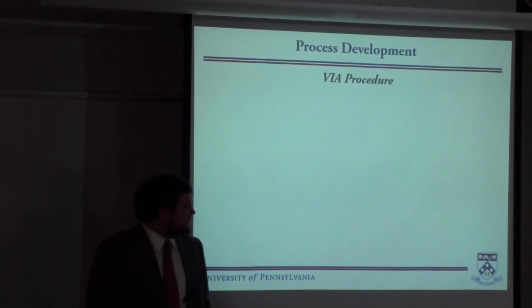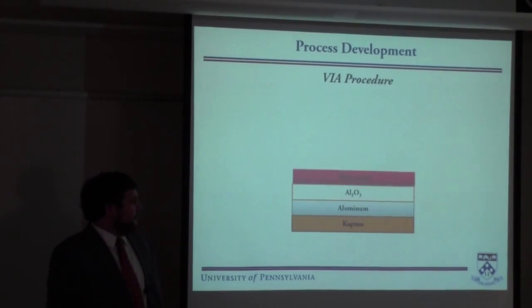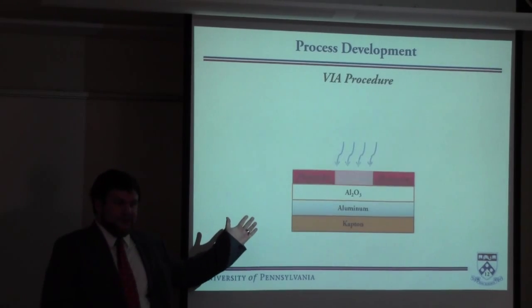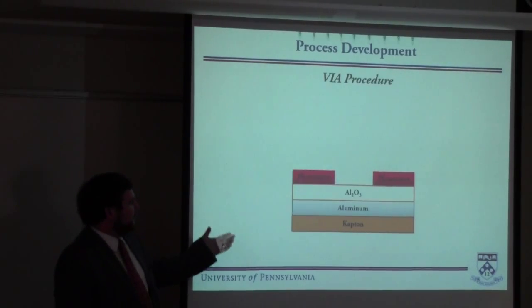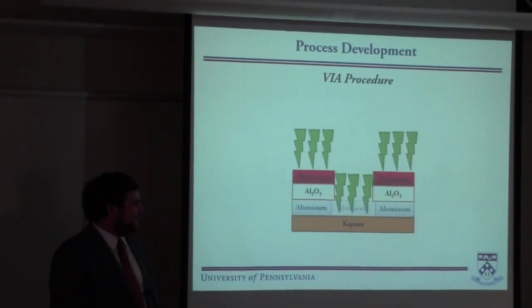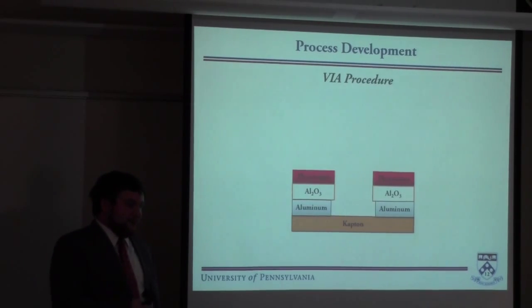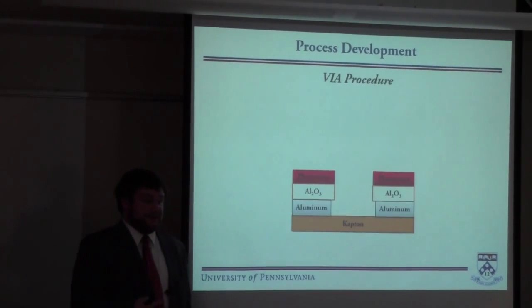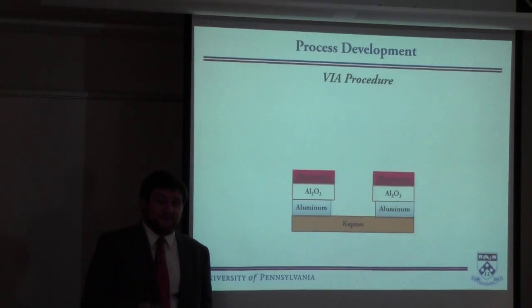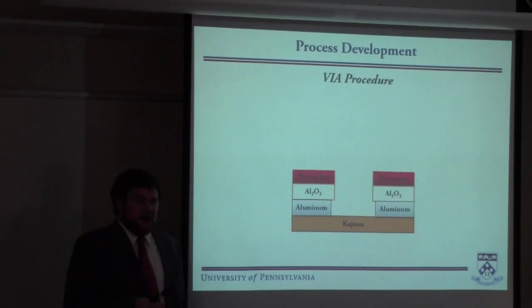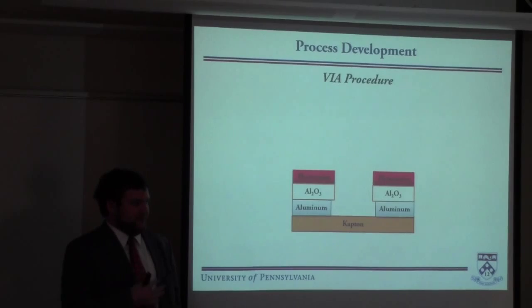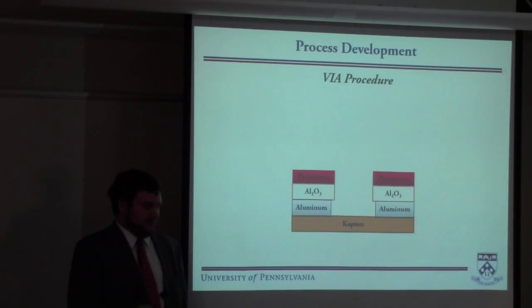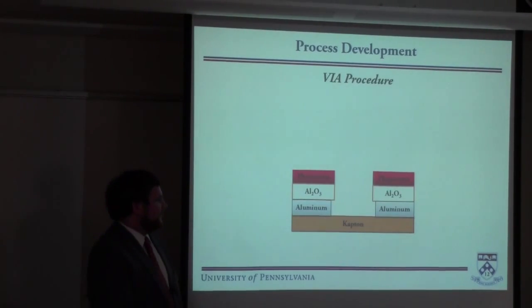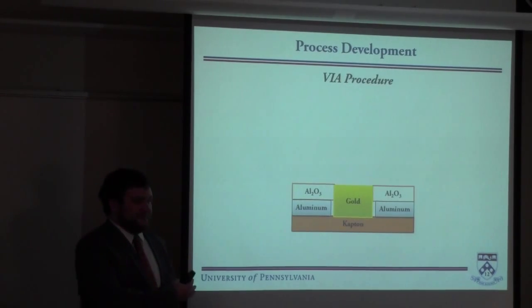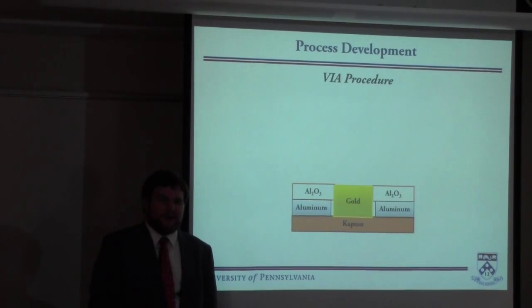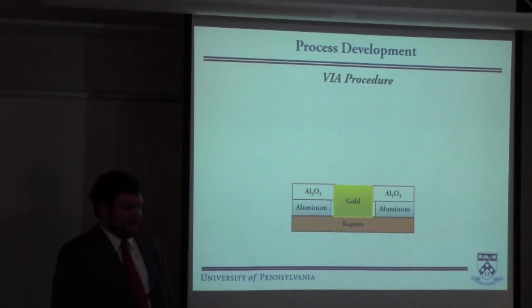So that led to some issues, because when we want to make a hole in the Al2O3, and we pattern the photoresist, and we do a chlorine plasma and etch down through, the chlorine plasma etches the Al2O3, but also etches the aluminum, and it etches the aluminum very, very quickly. And the tool that we have in the nanofab, we can't control it well enough to only etch partway through the aluminum. So we were etching away all of the aluminum, and when we tried to refill to actually make a via, we couldn't make contact. We had nothing to make contact to.